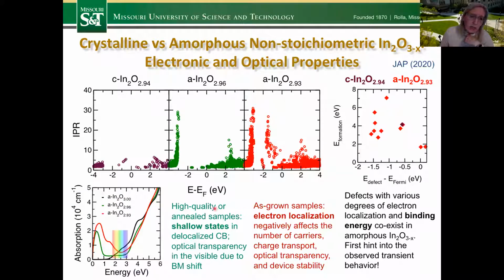So here, again, are the electronic properties of the indium oxide as a function of oxygen content. I showed you the very delocalized conduction band before for even slightly under-stoichiometric material. So this we call high quality annealed samples. We have only shallow, delocalized states. So the structure allows these defects and still be conducting with good conductivity, low scattering. But when we decrease the oxygen stoichiometry further, or maybe in as-grown samples, we may have a strong electron localization that negatively affects the number of carriers, the charge transport, as well as optical transparency and device stability. So all these defects appear below the Fermi level and affect the properties significantly.